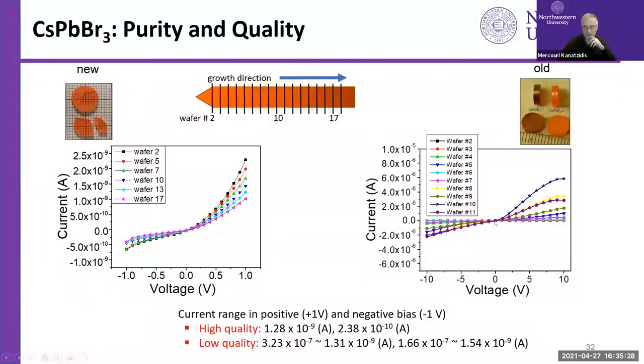And the same thing is shown here. So the high quality material will give you about 10 to the minus 9 amps to 10 to the minus 10 amps current. Low quality material would be worse by 1 or 2 orders of magnitude. So you can use that to assess.